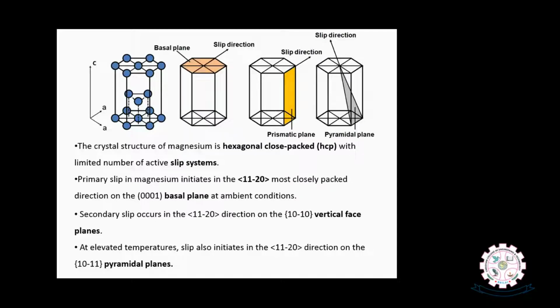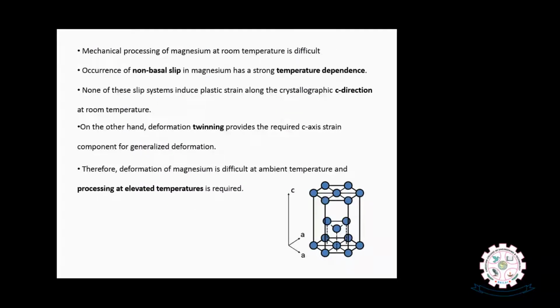That's why, due to the limited number of slip systems available at room temperature, deformation of magnesium is a mechanically difficult process. Occurrence of non-basal slip in magnesium has a strong temperature dependence. In order to introduce plastic deformation in magnesium, we need to heat magnesium. None of these slip systems induce plastic strain along the crystallographic C direction at room temperature.